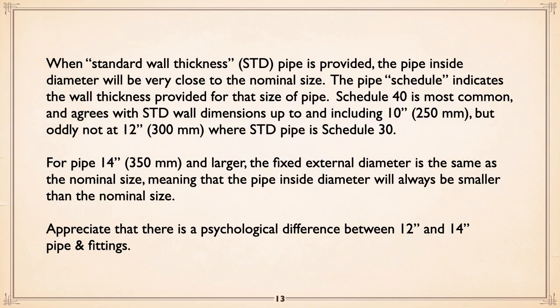When standard wall thickness pipe is provided, the pipe inside diameter will be very close to the nominal size. In other words, a 12-inch pipe may be 12 3/4 OD, but the ID will be relatively close to 12-inch. The schedule indicates the wall thickness provided for that size of pipe, Schedule 40 being the most common, and agrees with standard wall dimensions up to and including 10-inch, but oddly enough, not 12. At 12-inch, the standard pipe size is Sched 30.